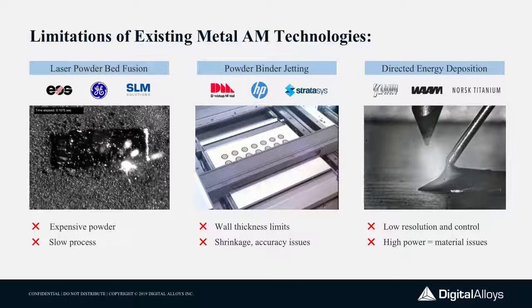Then there's direct energy deposition. Sciaky is here. I saw their booth. There are a lot of companies that do this now, but basically think of it as robotic welding. The processes that use wire typically use 2-3 millimeter wire, and then they have a very high energy heat source. They create a large melt puddle, and they push that around to build up a part with a weld bead. It takes advantage of welding wire, which is great because it's low cost. It's widely available. They can process materials at pretty high speeds, 5 to 10 kilograms an hour. Some of these machines can go up to that, but it's very low resolution. You don't have a lot of geometric complexity. It's made sense really for very large, simple aerostructures and industrial parts.